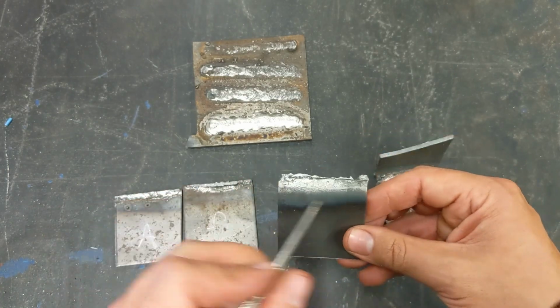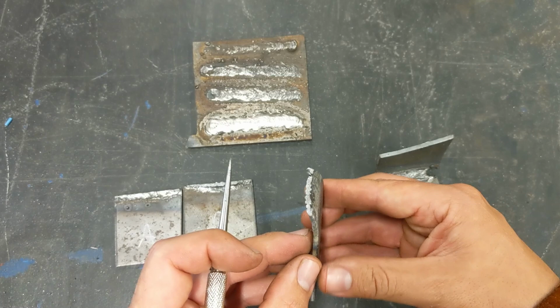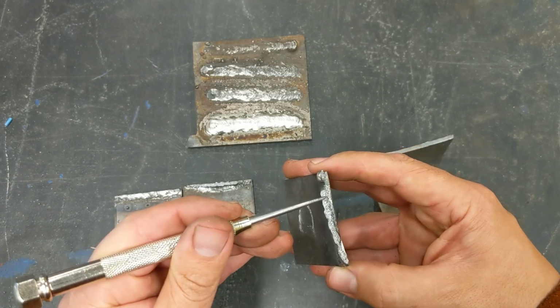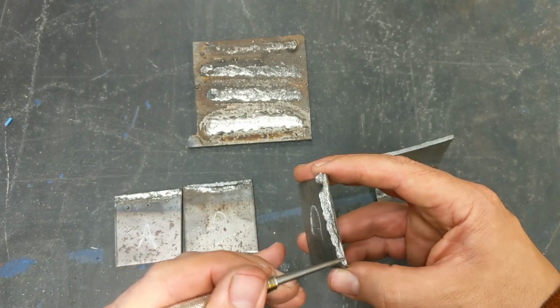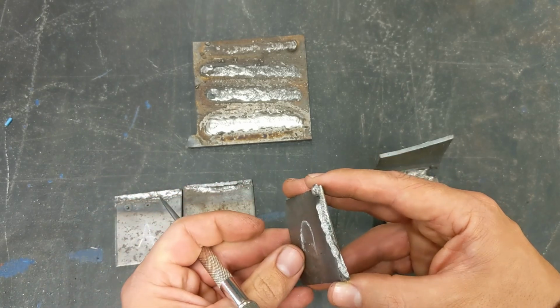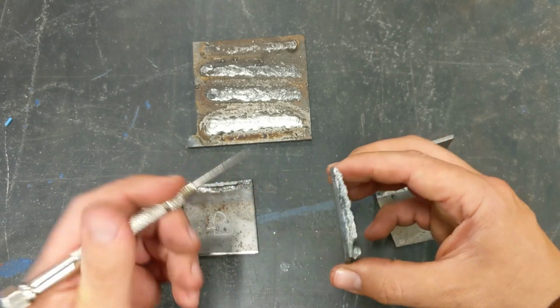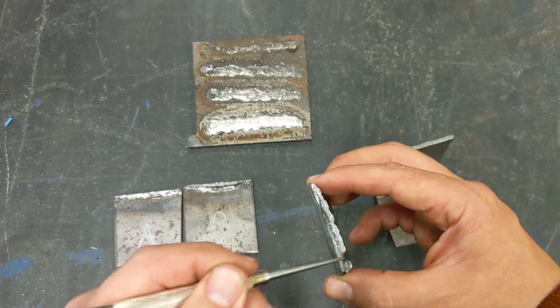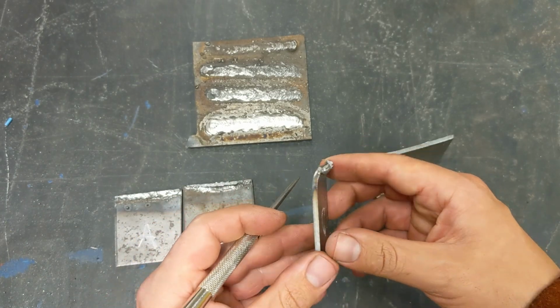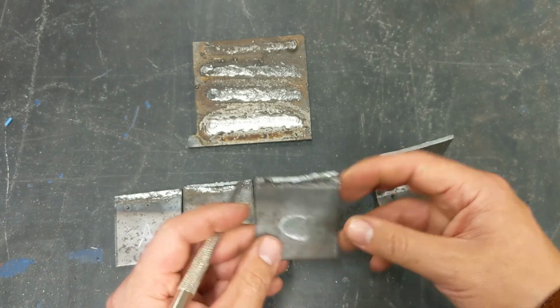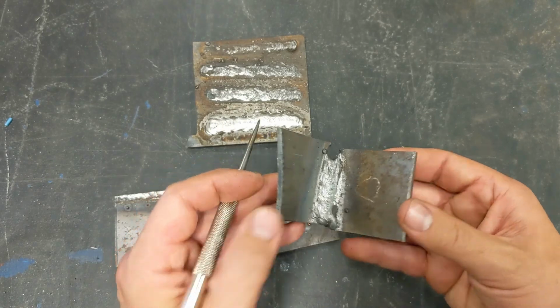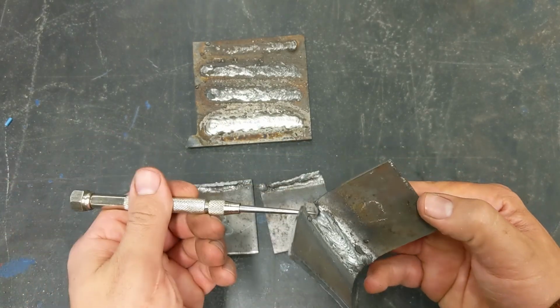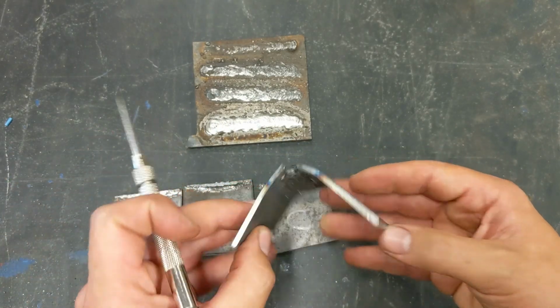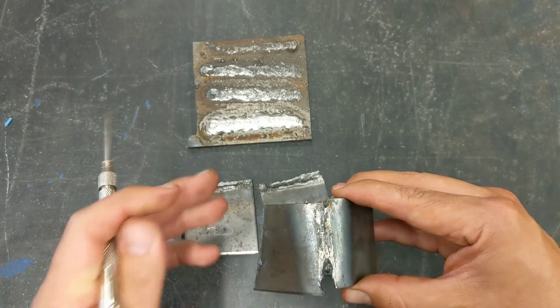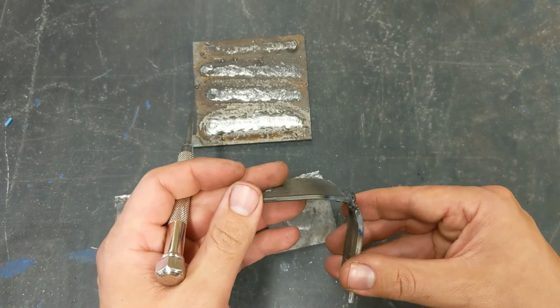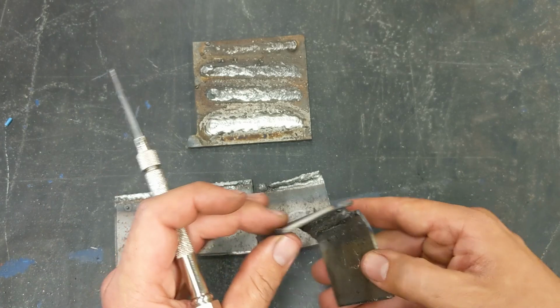Sample C, also some deformation all the way across, and here we can see some definite penetration, especially towards the end of the weld as it gets into the workpiece. You know, the workpiece had heated up as we were welding along. This one bent quite a bit before it broke. But lastly, sample D, remember I burned through a little bit through here, but sample D with complete weld penetration didn't fail at all. It managed to go past 90 degrees without breaking.